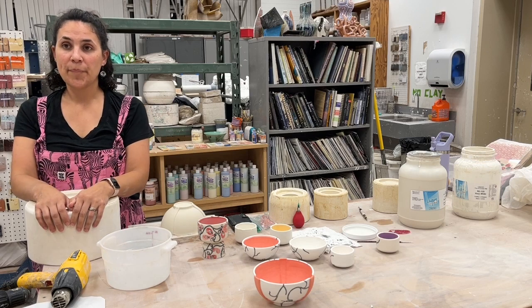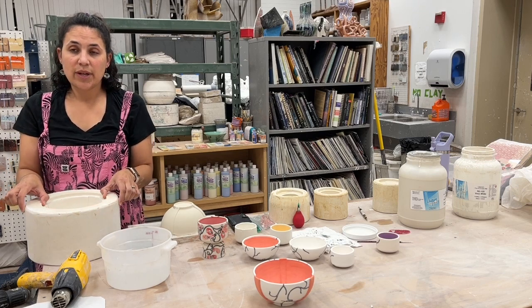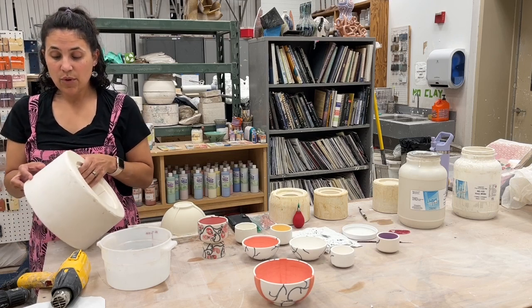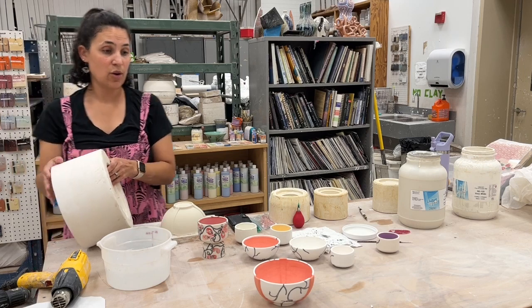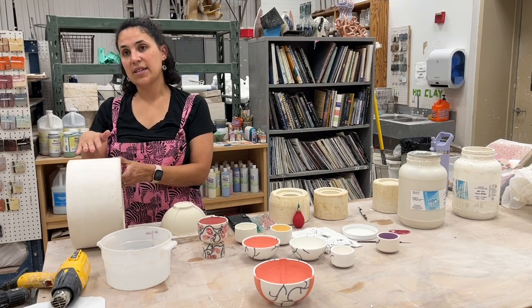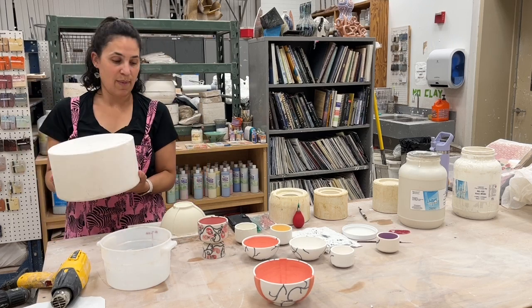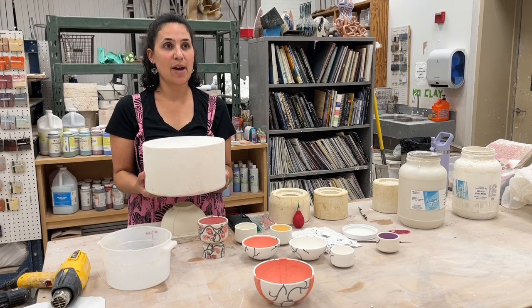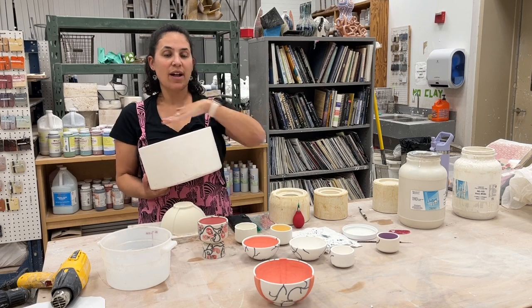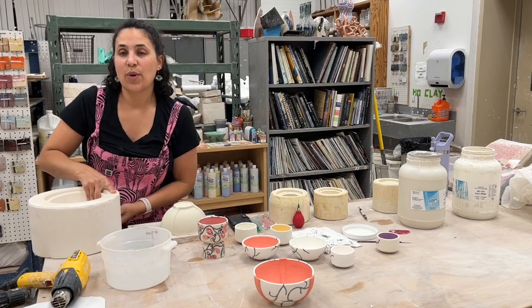The thickness of the molds — how do you determine how much for that bowl? I try to do at least two inches around the widest part. The more even the plaster, the better your absorption overall. I haven't had issues with it being thicker at the base to where I felt the need to adjust it.